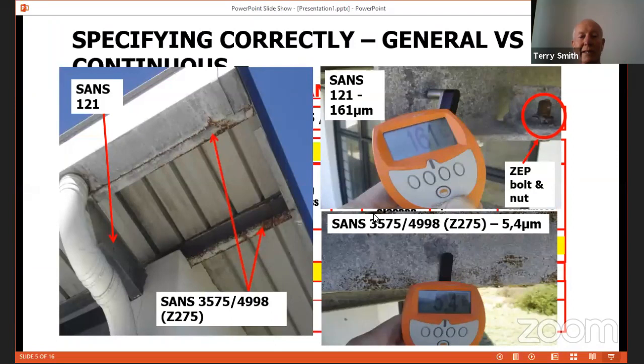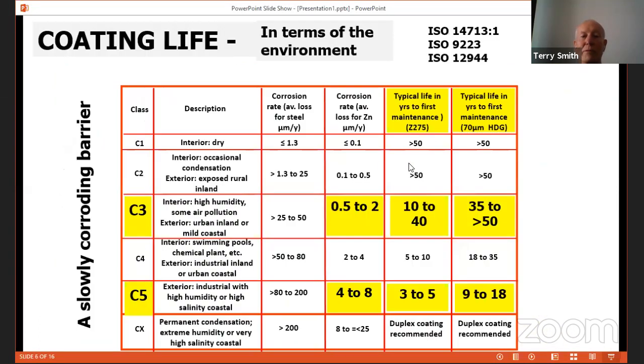Here's a site at Capricorn Park, which is about 400 meters away from the high water mark at False Bay, which is a very aggressive condition. Here you can see some trusses, which are hot-dip galvanized to SANS 121, coating thickness around 161 microns. All the purlins were only continuous galvanized Z275, with a coating of about 5.4 microns, and in some areas got red rust. And that's 3 years in a C5 marine atmosphere.